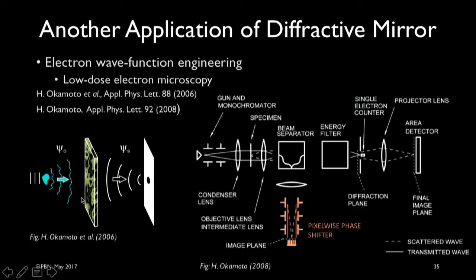However, if we guess the structure wrongly, and we place the wrong diffractive element here, what would happen is that we cannot focus the modified wave function. We actually further scatter the wave function, and we would not see on the detector the electron being focused on a spot. So by using this system, we can get yes or no answers to the guesses we make about the structure of the sample with only one electron. That's the idea of low-dose electron microscopy: if you have some idea of what the structure might be and guess it correctly, with one electron, potentially, we can know what the structure is. This could also be done in reflection.